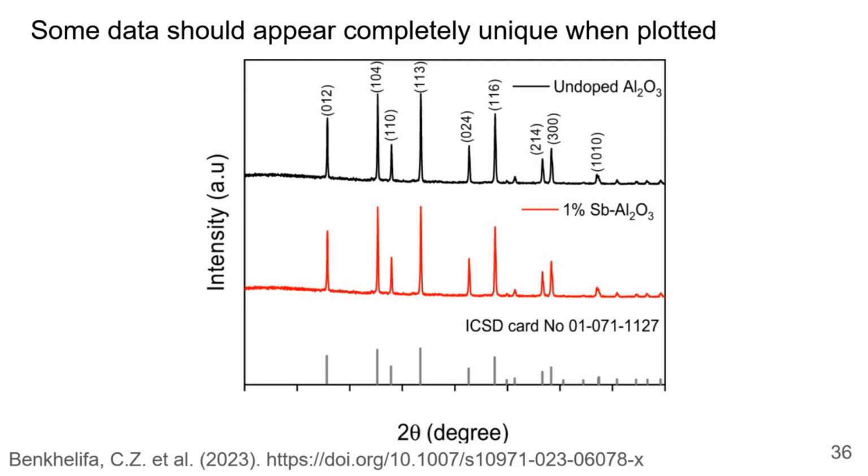Not only are the peaks in the same position, but the noise in the background is exactly the same. This is entirely unrealistic, even if these were the same sample. If they're two different diffraction patterns, they are expected to be entirely different. So this is two diffraction patterns that are identical in the same publication.